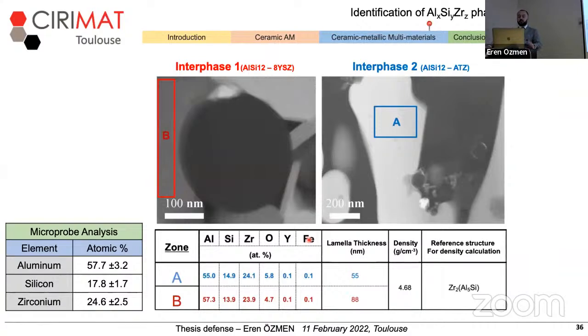So the question remaining still was, what's the exact composition of this ternary phase? To calculate the elemental atomic ratio of these two similar zones, I needed two pieces of information: the thickness of this lamella and a density. Then I was able to calculate the atomic percentage of each element existing in this area. To calculate the lamella thickness, I used a model and a software that gives you the thickness data. And then I took a reference structure to estimate the density of this ternary phase.